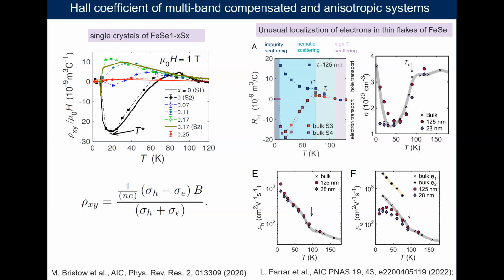So a potential explanation is that there are some scattering processes which are very strong in certain directions, as if those electrons which are involved in those processes do not contribute to conduction anymore. So we have a kind of short circuiting of the system, and we only see the most conducting channels, whereas others are not visible because of scattering.